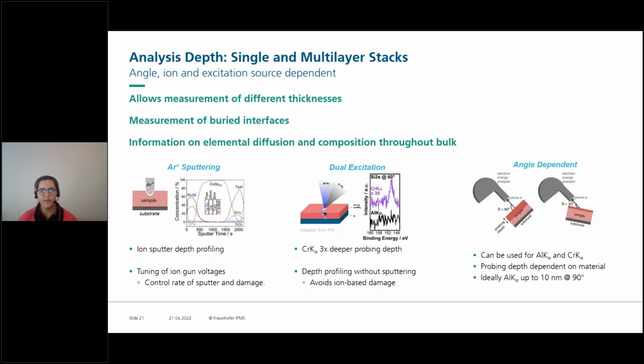We can also do angle-dependent measurements. This can be used for both aluminum and chromium Kα sources. So here, for example, you have a sketch where you see your electron energy analyzer and your sample and the photoelectrons entering. If I am at 90 degrees, I have a larger probing depth than if I am at 30 degrees. So you can tune how far or how deep through your sample you can measure.